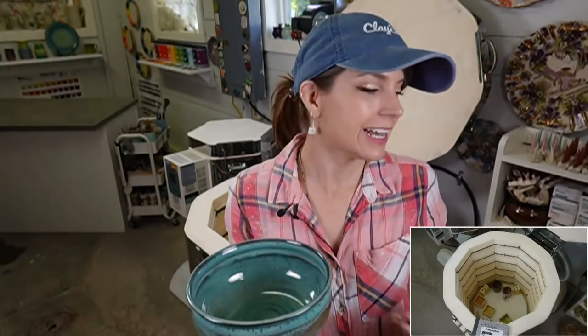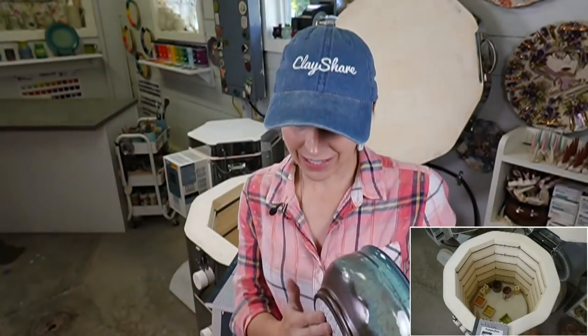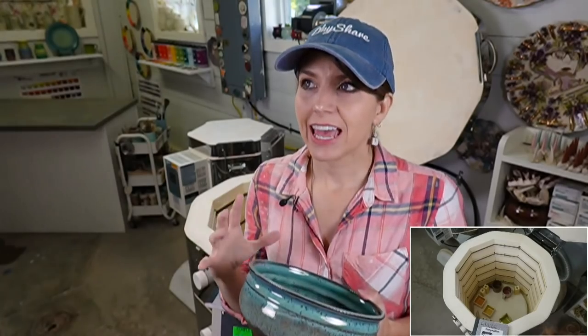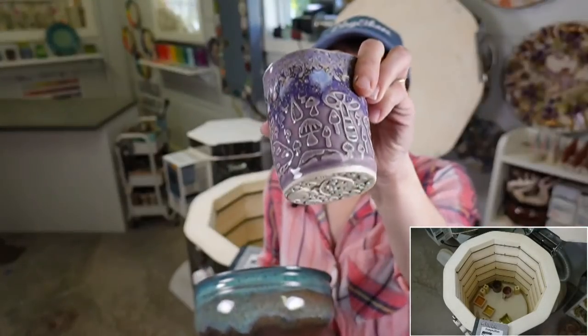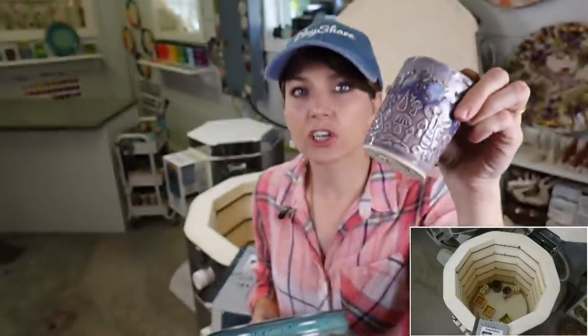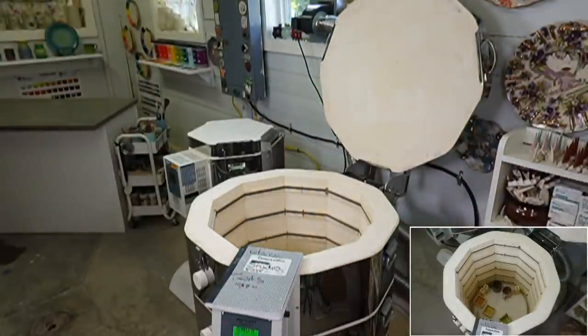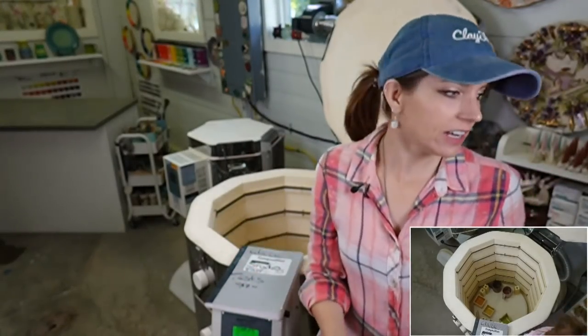There's nothing wrong with dark clays; it's just my preference to use light clays. Amaco celadons do fade at cone six — if you put four coats they might show up more. Cherry blossom and lavender celadon at cone five: look how beautifully purple that is! At cone six it's going to go more gray. Knowing your clay, your glazes, and your firing temperature gives you the best possible results.